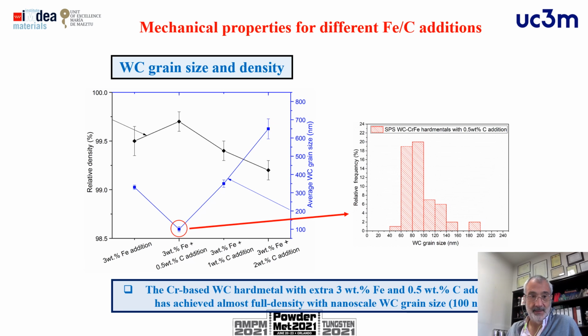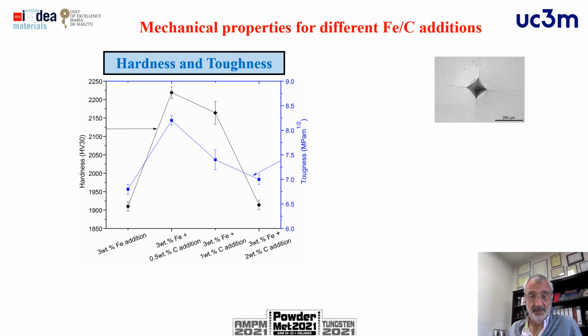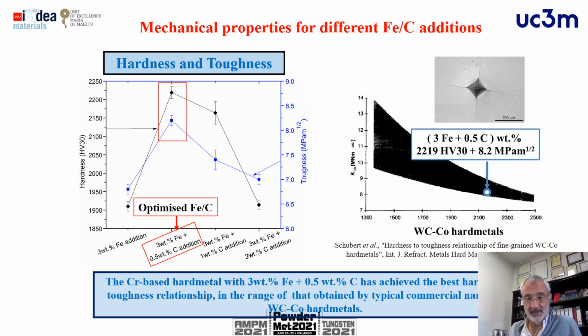Here we have the relative density that we can reach and the average tungsten carbide grain that we can reach with a combination of 3% of iron and 0.5% of carbon. And you can see here how this combination of iron and carbon with the new binder can allow us to reach the lowest level of the tungsten carbide grains and the highest level of relative density. And also, if we analyze the properties by the indentation method, the fracture toughness of this material can reach levels of 8 or 8.5 megapascals per meter, and relatively high levels of hardness over 2200 Vickers.